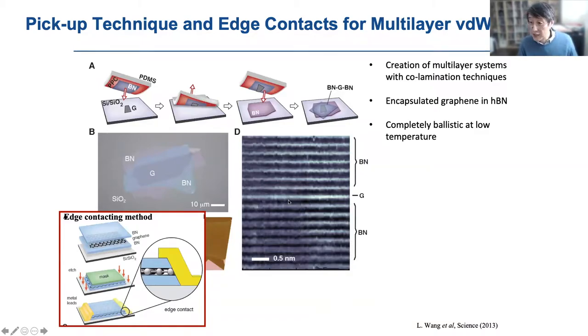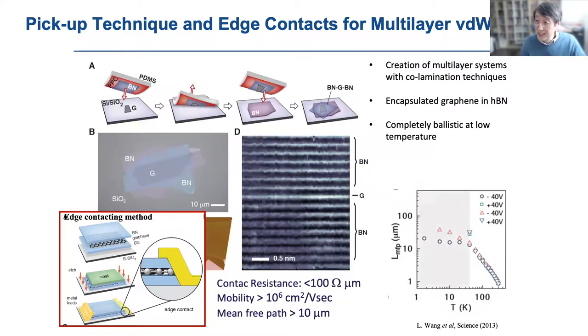It turns out you can make devices such that the electron mean free path is extremely long, something like a 100 micron length scale, in this type of device with extremely efficient contacts. So in terms of material quality, although this started only say 5 years, not more than 10 years ago, the quality you can achieve now in this type of system, at least graphene encapsulated in boron nitride, almost catches up with the quality of the electronic system you can achieve in gallium arsenide heterostructures, with mobilities of tens of millions of centimeter squared per volt-second. So I think that's a really exciting achievement in this field.